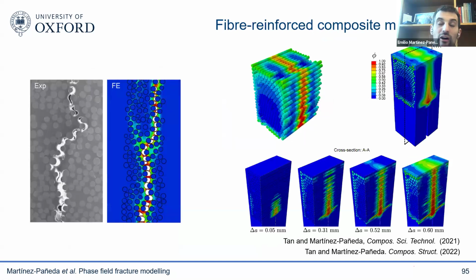We also did quite a lot of work on fiber reinforced composites. And I find this very interesting not only because we get a good agreement with experiments, you can see this here. Basically here we're using the phase field to simulate the evolution of cracks in the matrix, in the fibers, and the fiber matrix debonding, where we have also done simulations using cohesive zone elements. In fact, what you see here is that example. We're using the phase field to predict cracking in the matrix and the fibers, and then cohesive zone elements to predict the debonding between the matrix and the fibers.